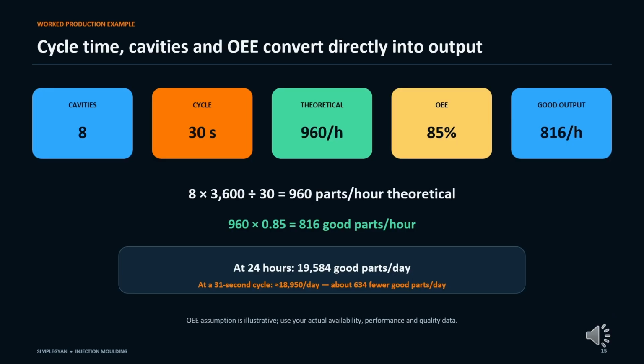Here is a practical output calculation. 8 cavities multiplied by 3,600 seconds per hour, divided by a 30-second cycle, equals 960 parts per hour theoretically. If overall equipment effectiveness is 85%, good output becomes about 816 parts per hour, or 19,584 parts in a 24-hour day. Stretch the cycle to 31 seconds and at the same OEE, daily good output falls by roughly 634 parts.